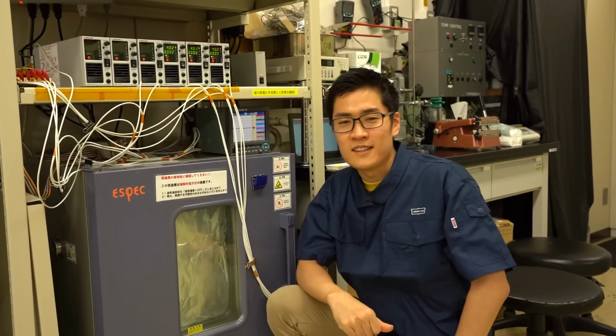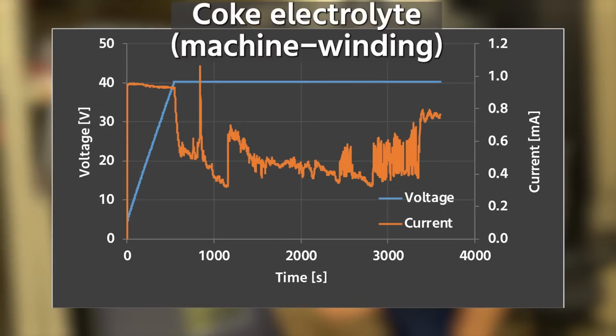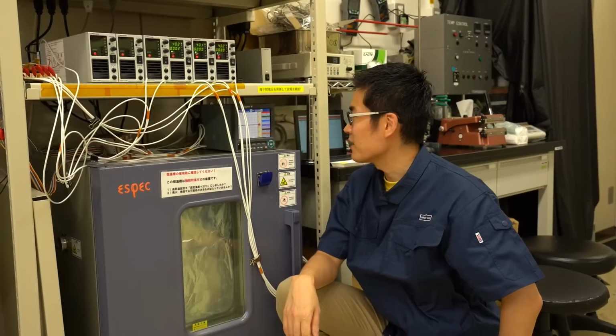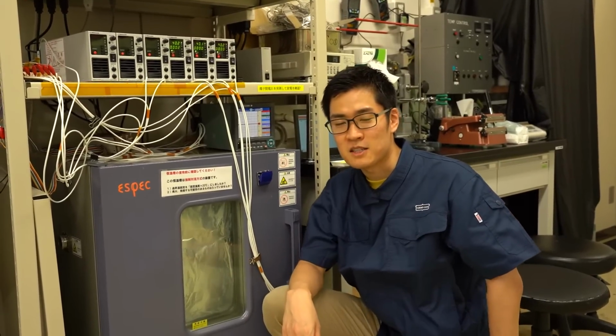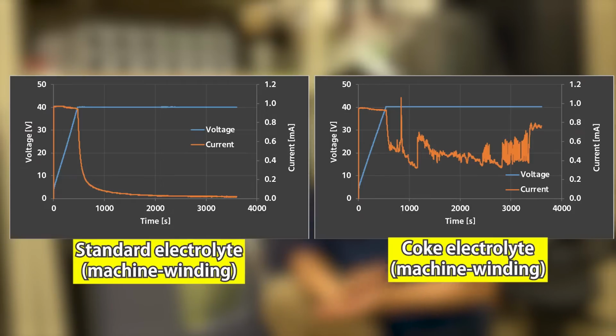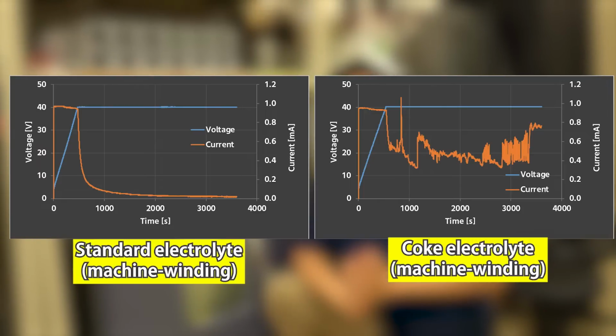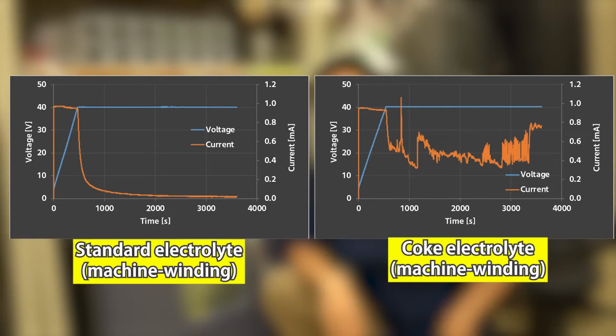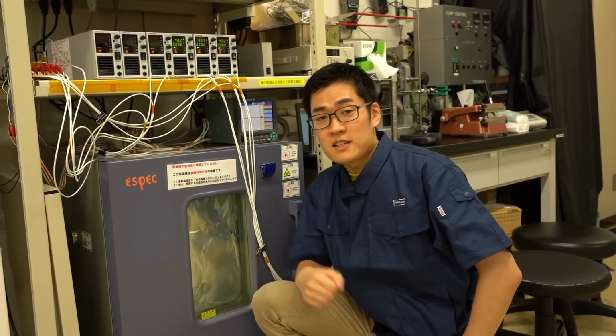There's a problem with the coke ones. The capacitors in which coke is used as electrolyte. Tremendous amount of leakage current is flowing, about 10 to 20 times as the other capacitors. What this means is that the damages on the surface of the foil are not healed yet. Current is leaking from the damaged areas. Let's wait until the reforming process is finished.